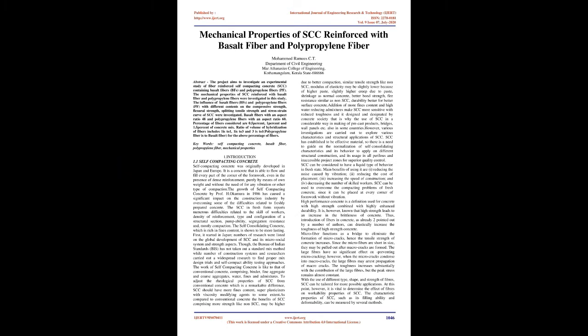Numbers of research were listed on the global development of SCC and its microstructural system and strength aspects. Though the Bureau of Indian Standards, BIS, has not taken out a standard mix method, a number of construction systems and researchers carried out widespread research to find proper mix design trials and self-compactability testing approaches. The work of self-compacting concrete is similar to that of conventional concrete, comprising binder, fine aggregate and coarse aggregates, water, fines and admixtures. To adjust the rheological properties of SCC from conventional concrete, which is a remarkable difference, SCC should have more fines content, superplasticizers with viscosity modifying agents to some extent.